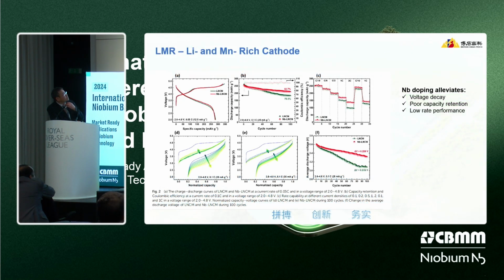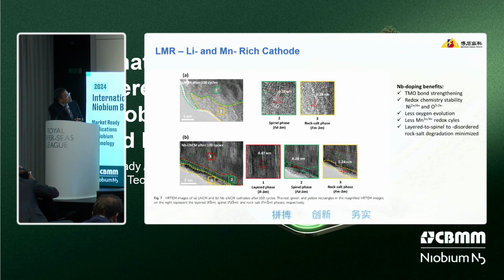Okay, the third one is the LMR. For LMR, of course, actually there are a lot of chemical compositions and a lot of chemical structures for this kind of material. And also a lot of research work has revealed the niobium role, for example, how to help with voltage decay and the poor capacity retention and the rate performance, and also how niobium strengthens the TM-O bond, the stability of the redox chemistry, and also less oxygen evolution and degradation.